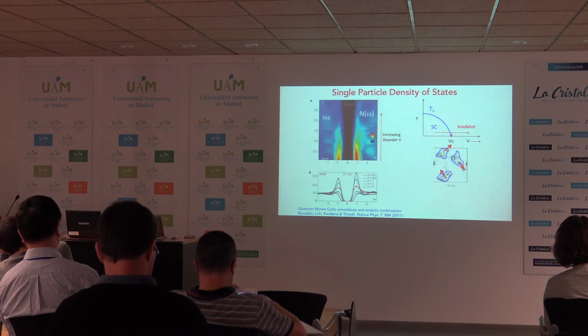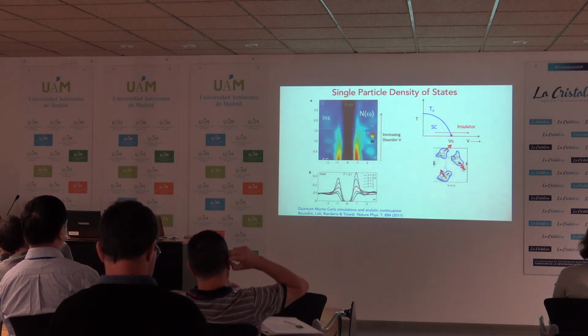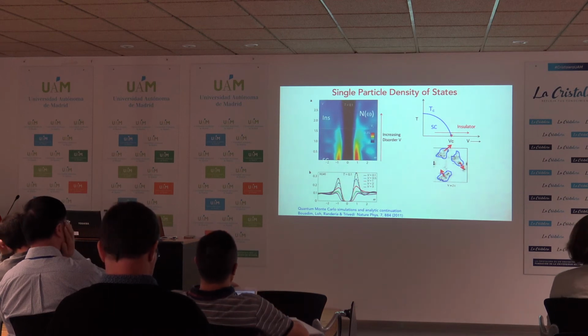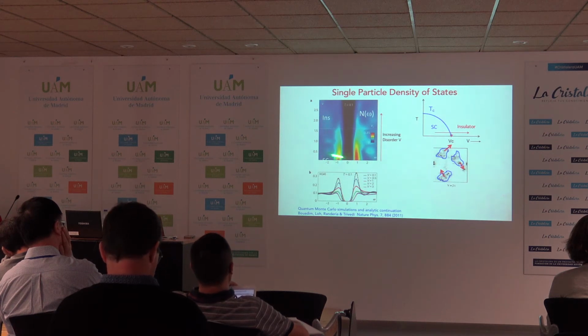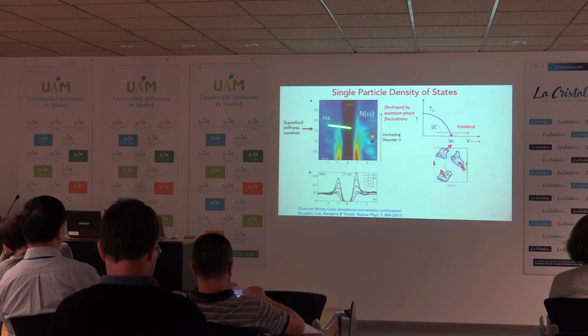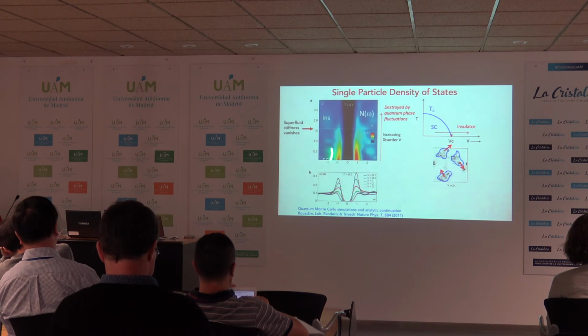Okay, a few more. This is like ramping up now our color plotting abilities. So these are all theoretical results showing now a cut like this at low temperatures. This is the single particle density of states. And you see the hard gap remains, so the hard gap continues through the transition. The transition is indicated by this white line here, which is where the superfluid density vanishes. So this is the superconductor, that's the insulator. The hard gap doesn't know about it, but the coherence peaks do vanish around the critical point, but really this sharp transition is obtained by seeing where the superfluid density vanishes.